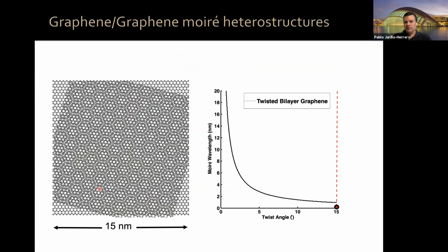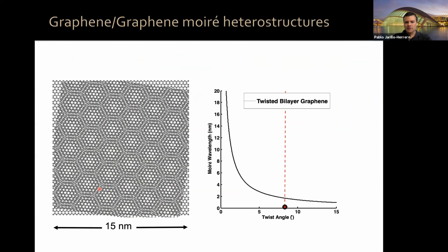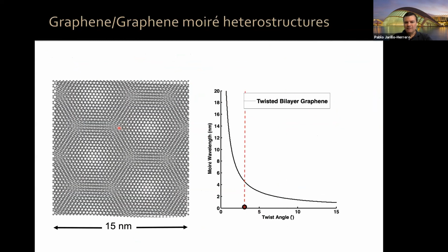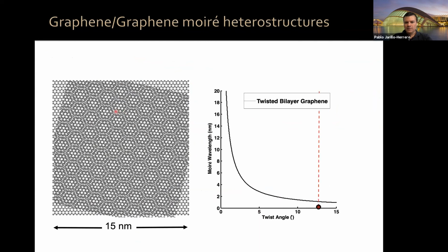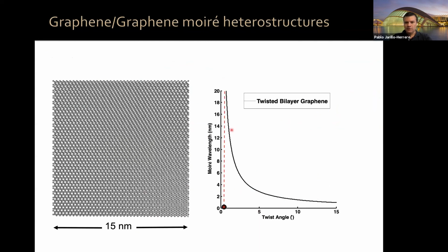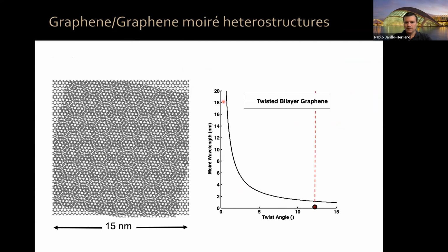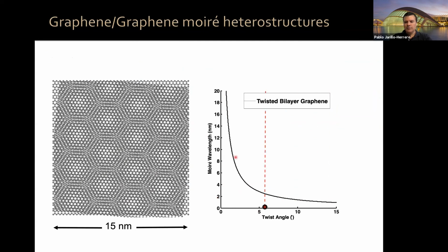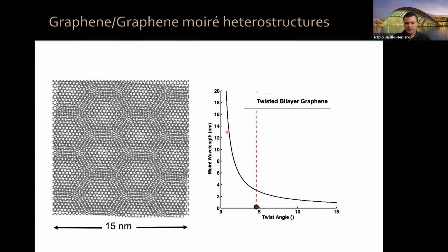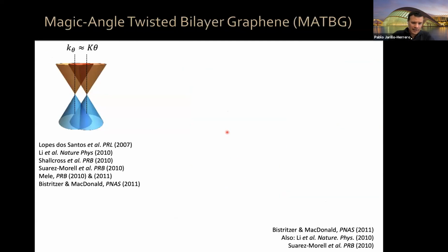Now, if you put graphene on top of graphene, a Moire pattern develops. The Moire wavelength, the distance between the soccer balls here on the screen, can go all the way to infinity as you get closer and closer to 0 degrees, okay? And it's roughly proportional to 1 over the twist angle. Now, in momentum space, these are the energy momentum relations of the Dirac cone in layer 1 of graphene and the Dirac cone in layer 2 of graphene. Their separation in momentum space is proportional to the twist angle for small angles.